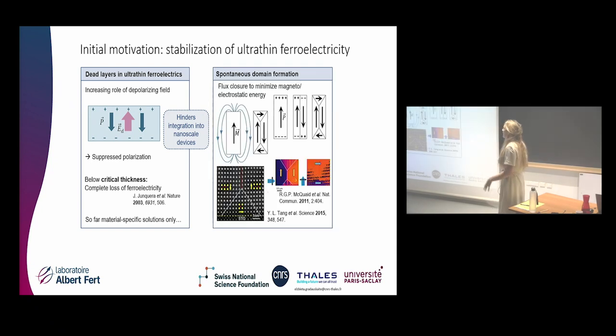For my work, we got a bit inspired by how domains form naturally in ferroelectrics and ferromagnets. You must have all seen such beautiful flux-closure domains forming naturally to minimize magneto- and electrostatic energy. While mostly known for ferromagnets, they also exist in ferroelectrics on both mesoscale and atomic scale. So that clearly seems to be beneficial for the system. In fact, if you have a closer look, there's always an in-plane polarized area and an out-of-plane polarized area. That's the motif of flux closure. And that was the idea of this work: can we somehow put an in-plane ferroelectric and an out-of-plane ferroelectric together in hopes that this will help to fight the depolarizing field?